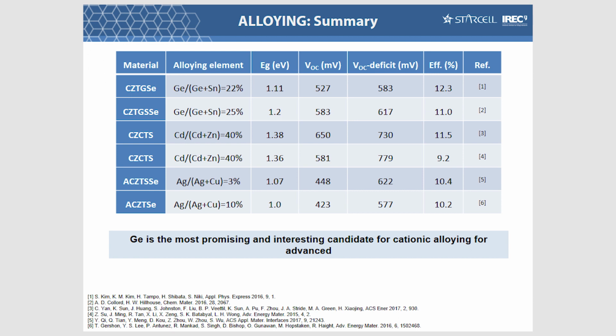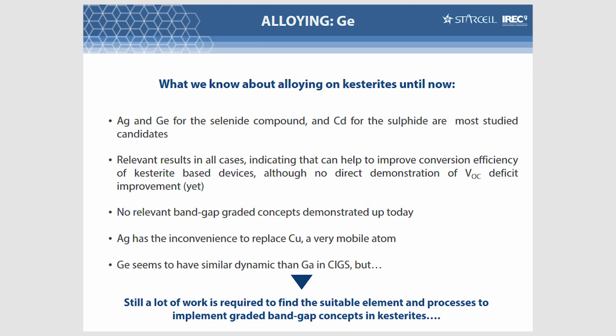And summarizing what we know about alloying, you can see here some of the best results reported using silver, cadmium and germanium, and it's clear that germanium gives really very high efficiencies, comparable to the pure tin compound. So this is, in my opinion, the most reliable result and the most reliable element to use in the future for a graded bandgap concept. I will skip this and go directly to the conclusions.